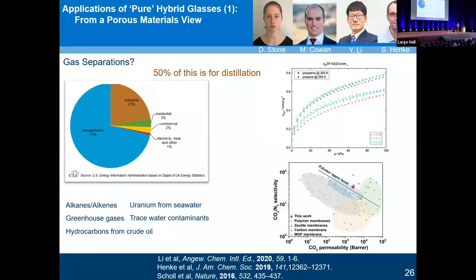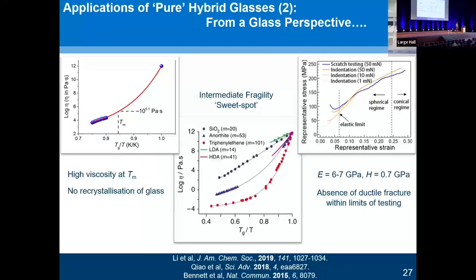So they've tried to show this, and Sebastian looked at ZIF glasses being able to separate different isomers of hydrocarbons. And then Yuanxiu Li has shown that a membrane formed from ZIF-62 actually performs really well in terms of CO2/N2 selectivity. So I'm really excited to see more work in this area and more work on looking at glasses from a porous materials point of view. But of course, we can also look at the glasses from a glass point of view.